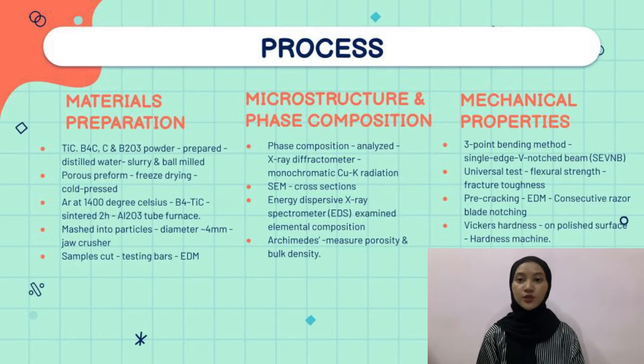The phase composition was analyzed by X-ray diffractometer using monochromatic Cu K radiation at 40 kV and 40 milliamperes. Scanning electron microscope had been used to analyze the characterization of cross-sections of the cut samples that had been polished. Meanwhile, the elemental composition was examined with an energy dispersive X-ray spectrometer, or EDS. The Archimedes method had been applied to measure the open porosity and bulk density.